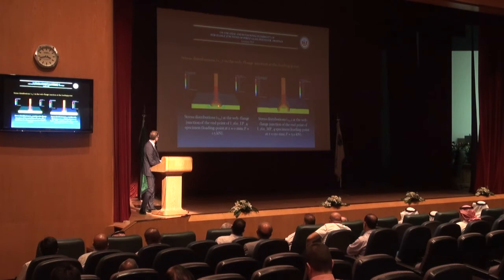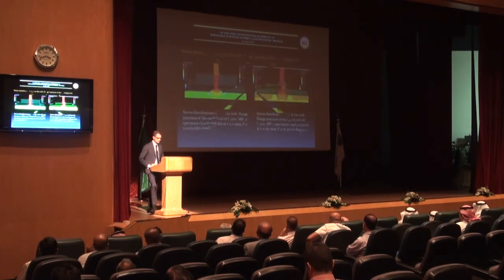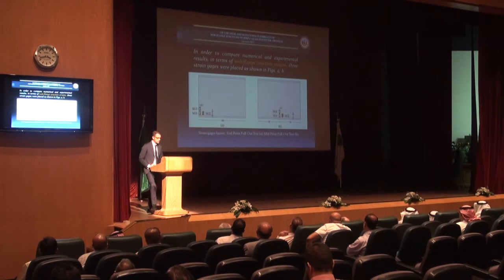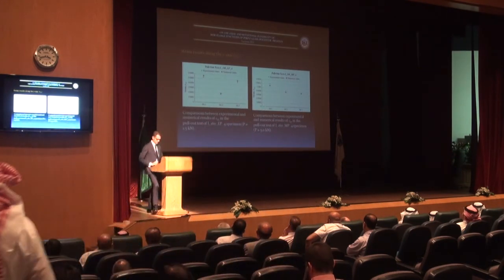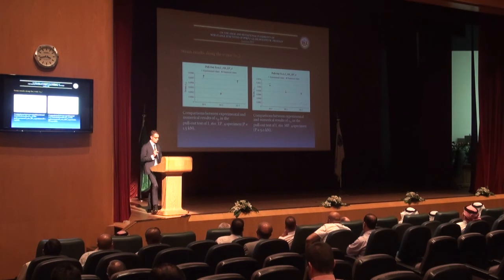And these are typical stress distributions at the web-flange junction. As you can see, the red color means that there is high stress concentration in these parts of the beam. And of course, in order to compare numerical and experimental results, we have used strain gauges to measure the strain and the displacement, and we find a very good agreement between the two results.